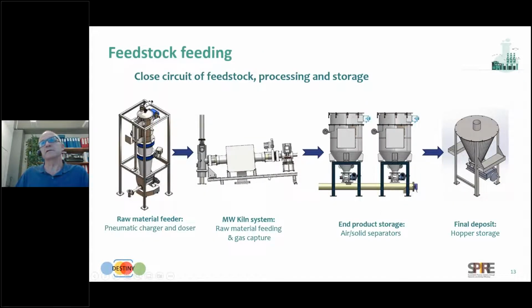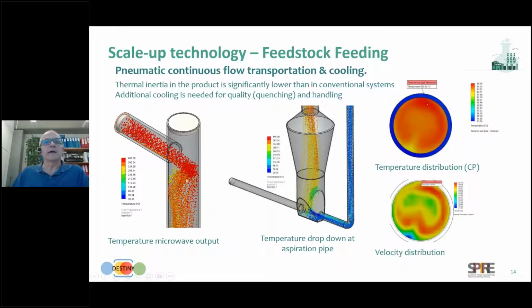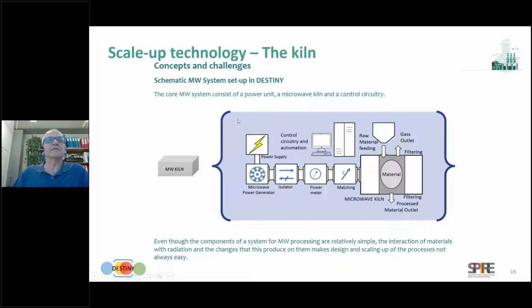So this is the feeding system. From the raw material feeder, all pneumatic, so it's quite fast. So we are using the fast system, and to final deposit storage, considering also the cooling system. Because it's pneumatic, it's easier and has some advantages, and is faster for the system. For the microwave, fortunately, the residence time is very short. So the material can go faster than in the conventional one.